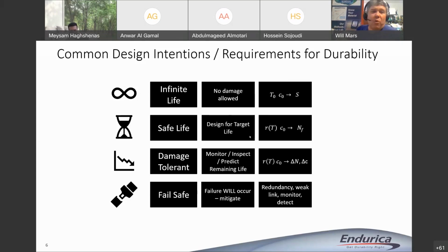Now, the safe life approach gets more complicated because suddenly it's not just a matter of checking whether we're above or below a certain line. Now it becomes a matter of, well, is the crack growing? How fast is it growing? And so now you have to get a lot more complicated in describing the material behavior. You have to describe stress strain behavior. You have to describe fatigue limit. You have to describe crack growth rate law. There's other effects: temperature dependence, rate dependence, strain crystallization. You start getting into all the things that make rubber very unique. But if you give me a load case, I can predict how many repeats of that load case, and I can compare it to my requirement, and that's the safe life approach.